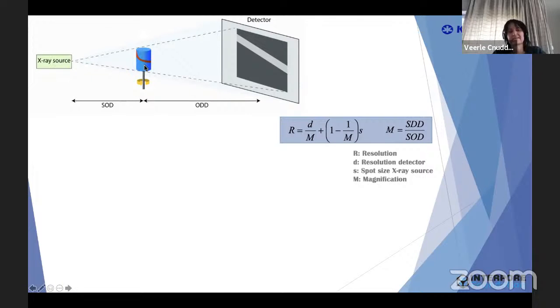This means that depending on the sample size, you will influence the resolution. So even if you have a machine that could reach resolutions up to, let's say, 800 nanometer in theory, that's possible, that's no problem with the micro CT system, but that will be under ideal conditions where you're also working at the maximum magnification.